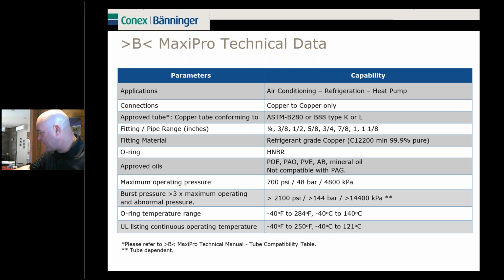So in Europe, 48 bar, that's equivalent to 700 PSI here in the US. So all our fittings are approved to 700 PSI. We do a burst test on them. We have a 2,100-pound burst pressure rating, and we're UL listed, and that's the important one here in the US. We're UL listed for -40 to 250 degrees on the fittings.